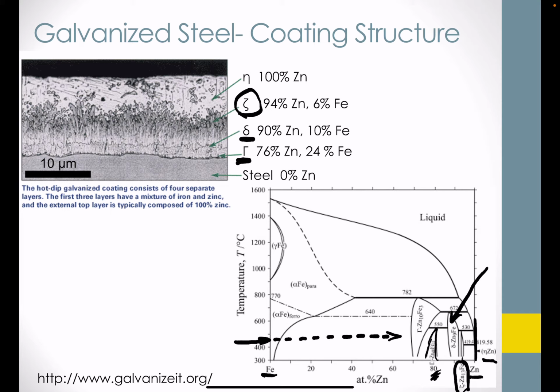there. Okay, so again, we can turn to the phase diagram to help us understand that different lattices of these two metals, zinc with iron, will exist in the material, and that may present itself in certain characterizations that we used. Here, the electron microscopy is distinguishing those layers based on the electron density of the two different metals and their packing pattern in the unit cells, and we're seeing contrast in the electron microscopy image. So clearly the atomic arrangement and packing of the zinc and iron here has presented itself as an opportunity for characterization in this SEM